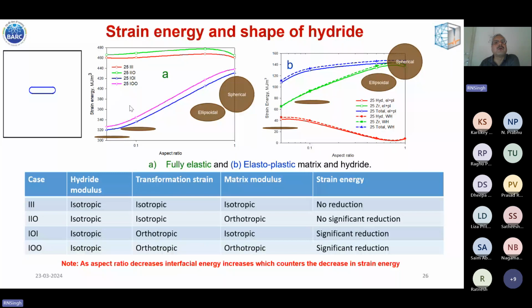So this curve is for elastic, using the elastic property of both hydride and the matrix. And this is for using the elastoplastic property of hydride and matrix. In both cases, the conclusion remains the same: an oblate, flat, thin sheet of hydride has the lowest strain energy.